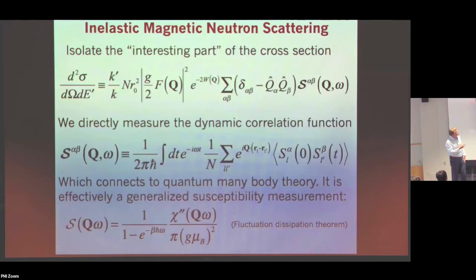For the inelastic scattering, everything can be formulated in terms of this dynamic two-point correlation function. Many of the theorists in the audience are very familiar with this kind of thing, or they may call it the Green's function. And we can directly relate what we measure to the imaginary part, the dissipative part, of the generalized susceptibility of the system. And with absolute units, we can in a sense think of neutron scattering as a very advanced magnetization measurement, where we have both wave vector and energy. So it's like an AC measurement, but also sensitive to spatial modulation. That's what we're essentially measuring.